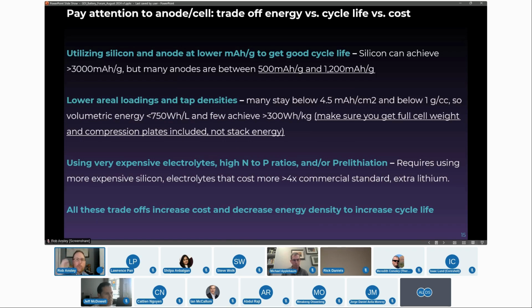Pay attention to the numbers. You need to find out, okay, silicon can do 3,000 milliamp hours per gram. What are you doing? What's your anode rating? Is your anode rating only 500 milliamp hours per gram because it's mostly carbon and you're doing a high N to P ratio? Is it 800? Is it 1,000? And what you will find out, without exception, is the harder you run the silicon, the shorter your cycle life. The harder you run the silicon, the shorter your cycle life.